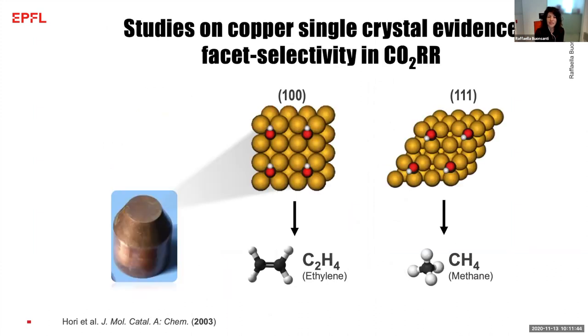A Japanese scientist, Hori, discovered that using single crystals, certain orientations of the copper surface are more selective for certain products. So in this case, the 100 surface is more selective for ethylene, and the 111 surface is more selective for methane. Of course, a single crystal is ideal to study the structure-property relationship, but it cannot eventually be implemented into an actual device.